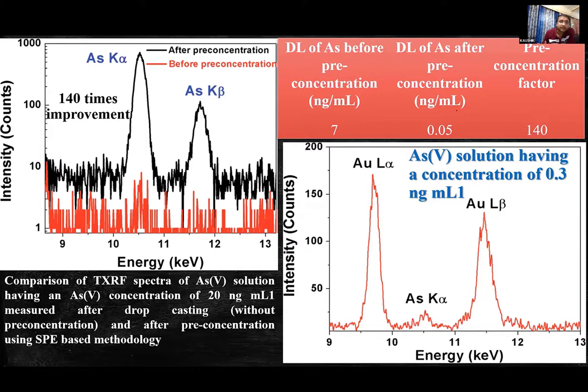You can see that this is a spectra of an arsenic 5 solution containing 0.3 ppb arsenic. Although arsenic is present at such a low concentration level, we can still see the peak of arsenic K alpha. So using this methodology, we could do the speciation study at such a low concentration level.